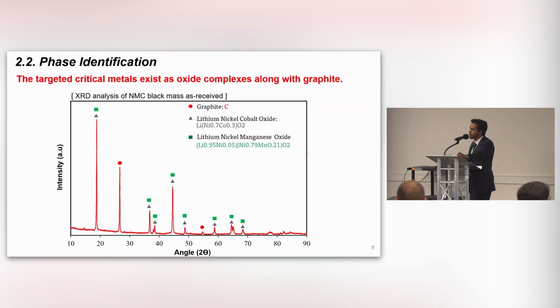We have also performed some XRD analysis in order to identify the crystal phases. You can see the main critical metals, lithium, nickel, cobalt, and manganese, exist as a complex oxide, and the carbon exists as separated graphite. Before applying any hydrometallurgical techniques, we need to understand how these critical metals exist, in what forms. In this case, we need to know how to break down this complex oxide so that it will be amenable to the leaching process.